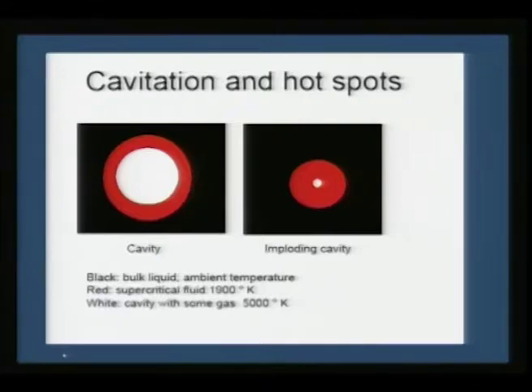Now cavitation and hotspots can bring out a lot of data that is very meaningful. You see the cavity here and an imploding cavity here, and the black region is your bulk liquid at ambient temperature. If you proceed towards the bubble, the red zone is your supercritical fluid, which can achieve temperatures up to 1900 Kelvin. The local areas are nearly at room temperature, but closer to the cavity you achieve around 1900 Kelvin, and the white space is the cavity trapped with some gas, where the temperature is of the order of 3000 to 5000 Kelvin, depending on the nature of the gas that is trapped.